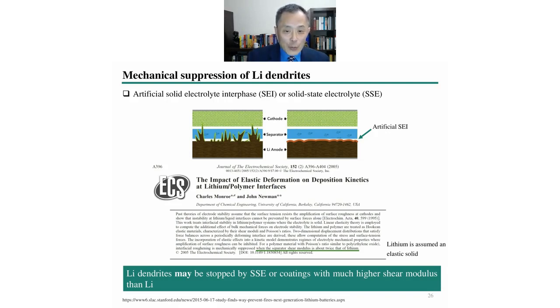The second approach is to use solid state electrolyte, which can be polymers or ceramics or polymer-ceramic composites. In this community, many people believe the shear modulus of the solid electrolyte should be 2 times that of lithium metal in order to block lithium dendrite penetrating through the solid electrolyte. And this model, of course, is based on the assumption that lithium deforms elastically during the operation, during dendrite growth. So this is a motivation for us to measure the mechanical properties of lithium at room temperature.